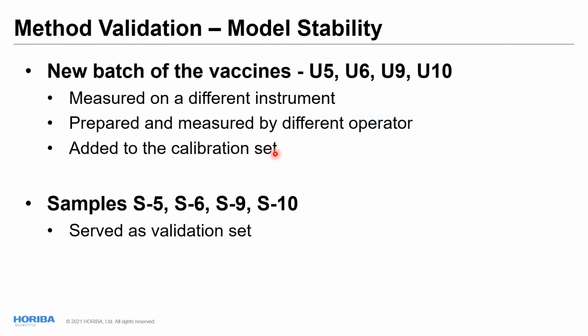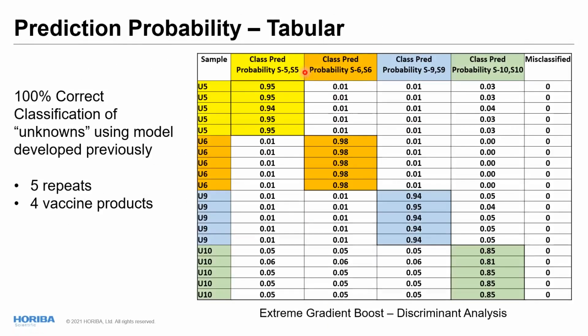So we got a new batch of vaccines. We call these the U series, different instrument, different operator. We added these to the calibration set, pulled these samples out for validation, and predicted against the model that we had created with the previous sample sets. And what we see here with this confusion matrix is 100% correct classification of these unknowns using a model that was developed on a totally different instrument and set of samples. These are 5 repeats of the 4 vaccine products.